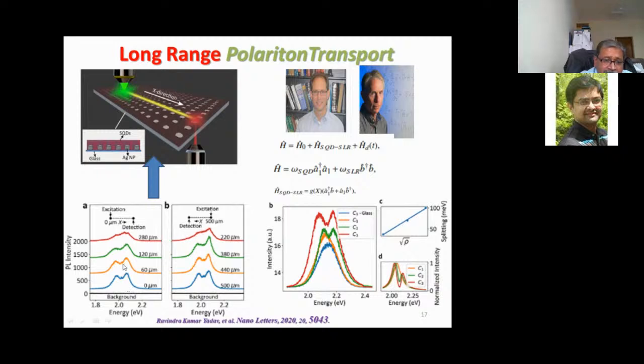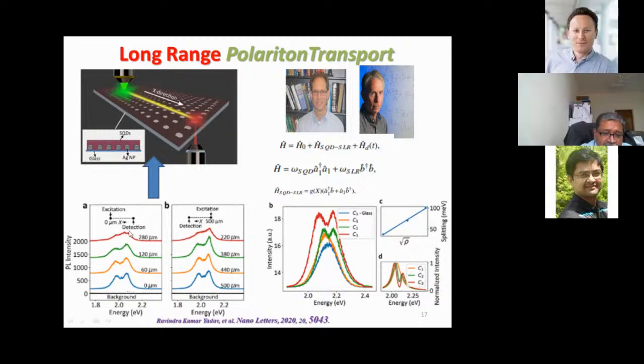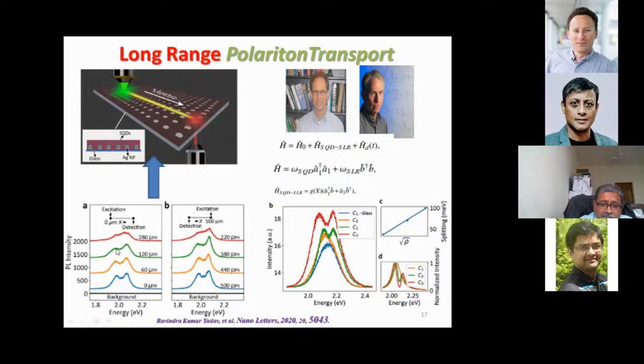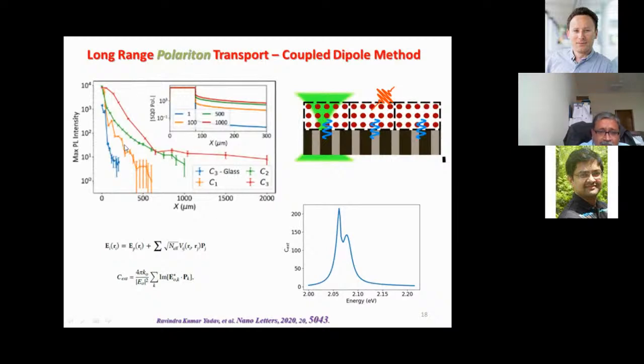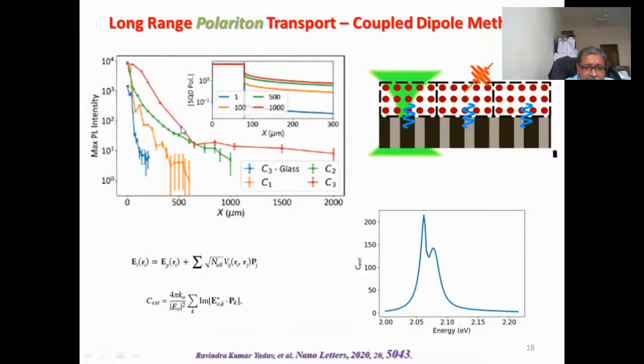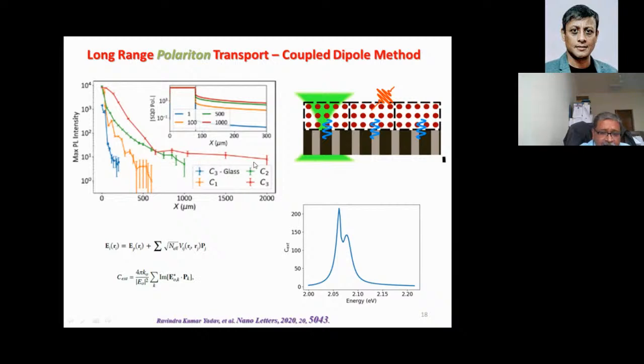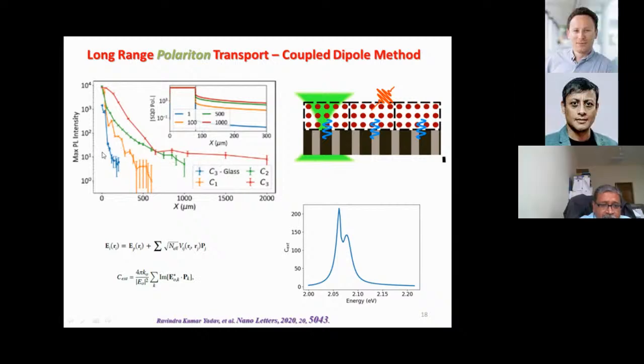But what we see in addition when we look at this spatial dependence is that as you go far away, very far away, significantly away from this excitation regime, we still see evidence of these modes propagating. So that means this seems to be propagating even far away from the excitation region, and that is very interesting. In fact, when we look at the intensity, you can see that it is going very far away.